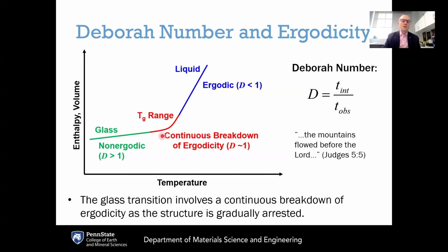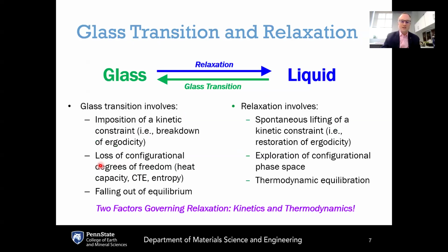Then if you continue to cool the supercooled liquid through the glass transition, we have a Deborah number that's greater than 1 because the relaxation time scales are much longer than our observation time. And when that happens, we have a non-ergodic system because time averages of properties are going to be different from ensemble averages in the glassy state. So the non-ergodicity of glass is one of the most fundamental features of the glassy state. And it forms the basis for all of the statistical mechanical descriptions of glass. So non-ergodicity is really one of the defining features of the glassy state.